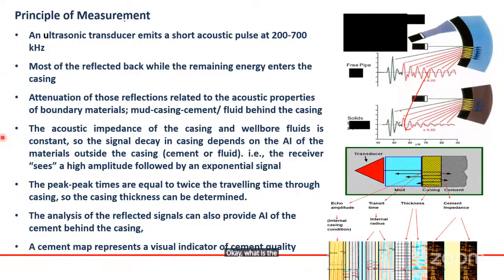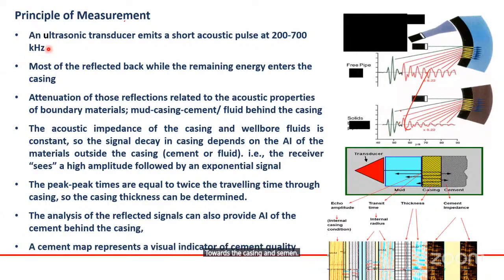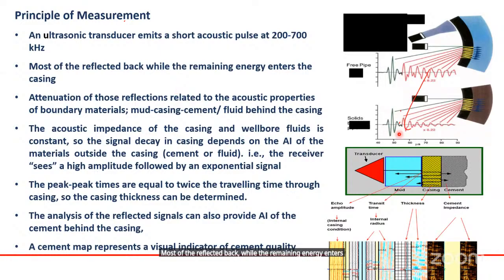Okay, what is the principle of measurement? We will talk about the signal or the pulse towards the casing and cement. What happens? An ultrasonic transducer emits a short acoustic pulse, most of it is reflected back, while the remaining energy enters the casing. As you see here, it sends a pulse and most of it returns, and some of it goes into the casing and to the cement. It enters the casing and is reflected, and some remains, enters the cement and reflects. So we receive a wavelet. The attenuation of this reflection is related to the acoustic properties of the boundary materials: mud, casing, cement. So based on these boundaries, the reflection will happen.